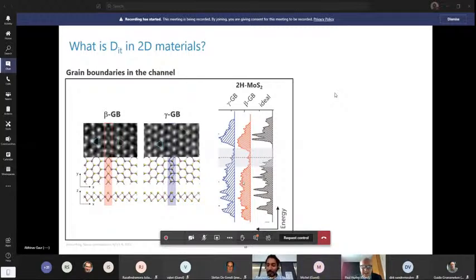It was unintended if we had different material thickness. With flakes of bilayer or trilayer material, we did not see a big difference in the DIT. It was more or less consistent, because I'm assuming that if it's coming from the channel, then even if you have a thicker material, maybe that's not going to impact it too much. So basically we did not measure very different thickness variations of the channel for the DIT. But we've gone from bilayer to 3 to 5 layers, and there we don't see a big change in the DIT experimentally.